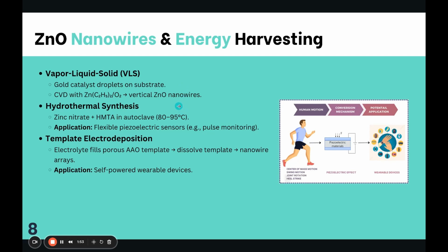Then comes hydrothermal synthesis. Precursors such as zinc nitrate and hexamethylenetetramine are used. The solution is placed in an autoclave and heated to 80 to 95 degrees Celsius. HMTA slowly hydrolyzes in water, releasing hydroxide ions. Zinc ions from zinc nitrate react with hydroxide to form zinc hydroxide, which converts to zinc oxide nanostructures. Controlled growth yields well-aligned zinc oxide nanowires on flexible substrates. It is ideal for flexible, low-temperature fabrication of zinc oxide on plastics or fibers.